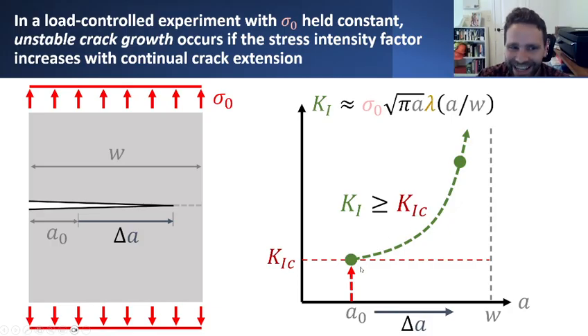So it'll do it again. The crack will try to continue to extend even more. And in doing so, it'll cause the stress intensity factor to go up even more. And it'll continue on in this fashion, with the crack continuing to extend and the stress intensity factor continuing to grow, until basically the crack extends all the way through the plate and cleaves it in two.